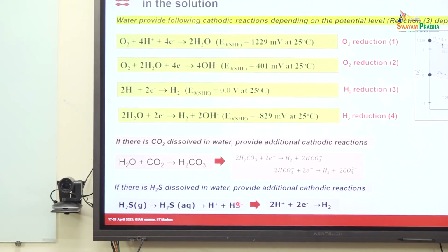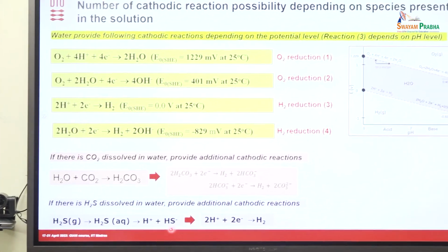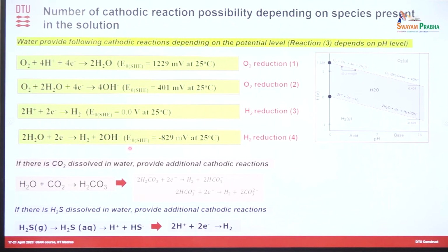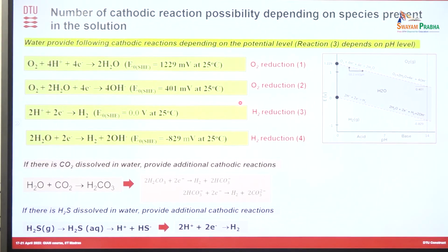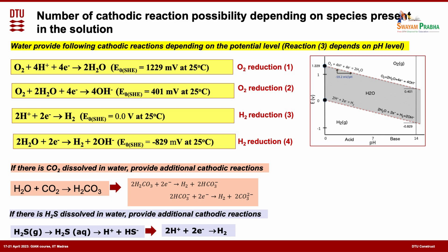H2S splits into H plus and HS minus, and this H plus can reduce like what we are seeing here. So removing the oxygen doesn't mean that there are no other things. Again, it depends on the corrosive systems. It's more complex than that. But removing the oxygen in a normal condition serves a lot of purpose.